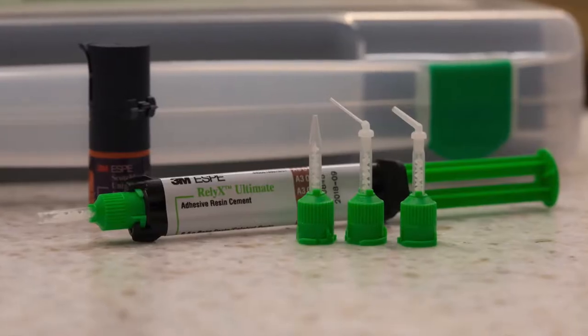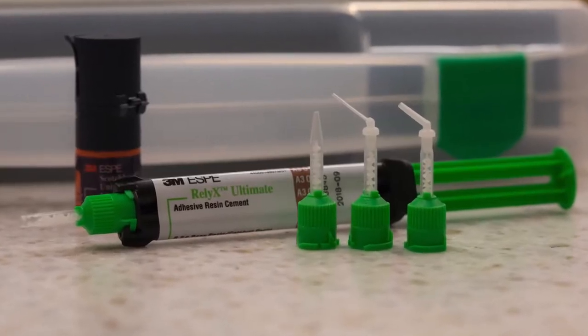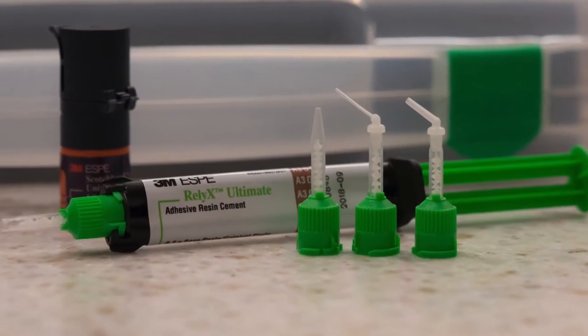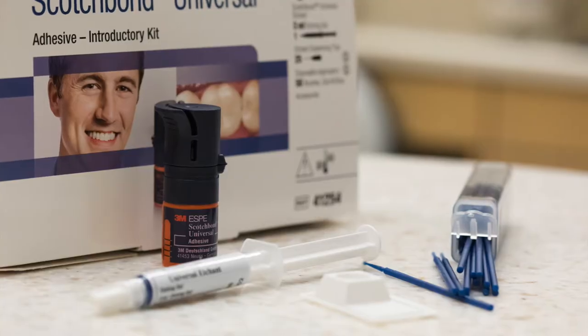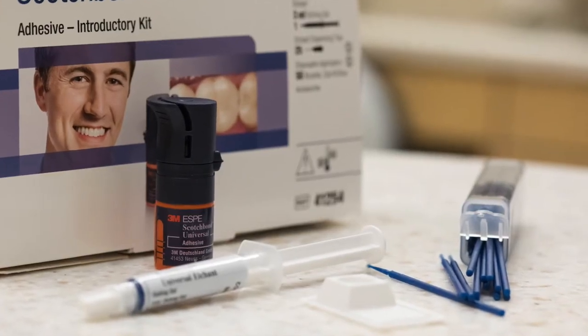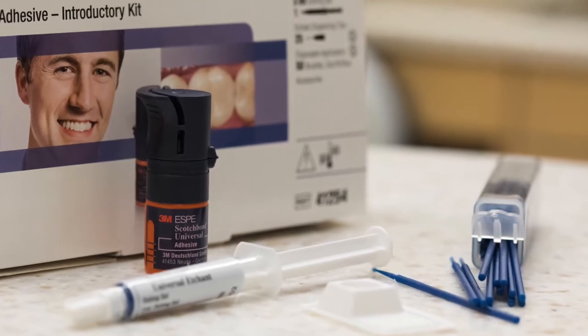In my clinic, we actually use the product Relyx Ultimate. It's a self-adhesive resin cement. And that cement actually contains a dual cure activator. And oddly enough, 3M recommends that you only use Scotchbond Universal with that cement. And so because the Relyx Ultimate contains a dual cure activator, you don't have to apply a separate dual cure activator or add that to the Scotchbond Universal prior to cementing the restoration.